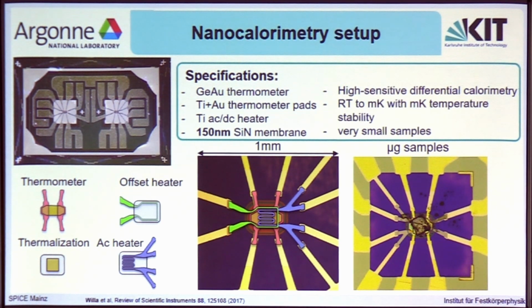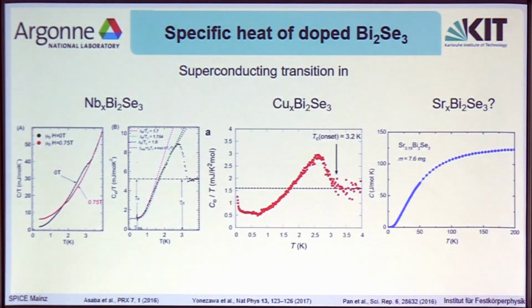Okay, and the first sample we actually wanted to measure with this setup was the specific heat of strontium-doped bismuth selenide. Why that? Well, actually because the specific heat of niobium-doped bismuth selenide and copper-doped bismuth selenide had been published very early on, showing nice specific heat jumps at the superconducting transition. However, for strontium-doped bismuth selenide, specific heat had been published without the mention of any superconducting transition, which you would naturally expect for a superconductor.